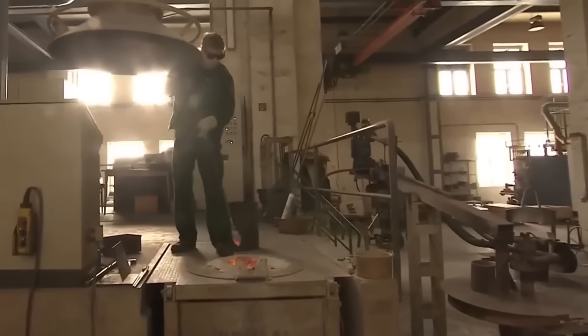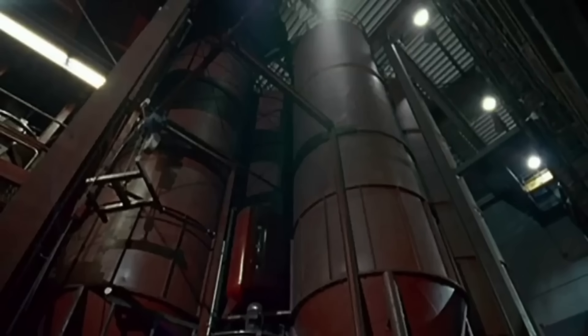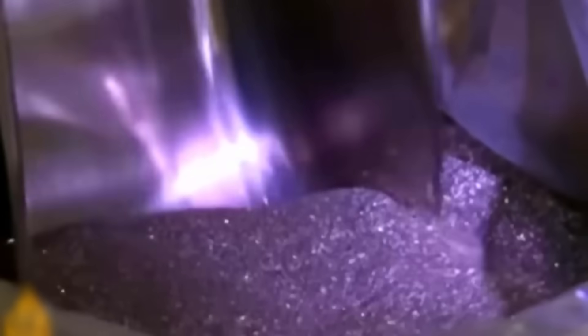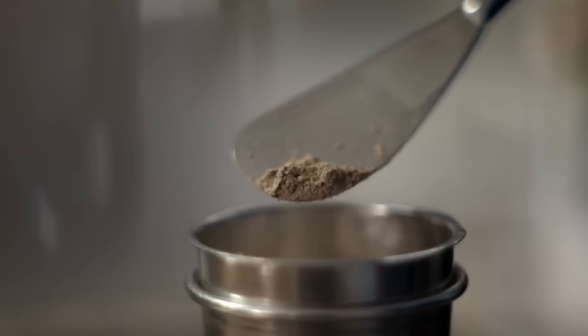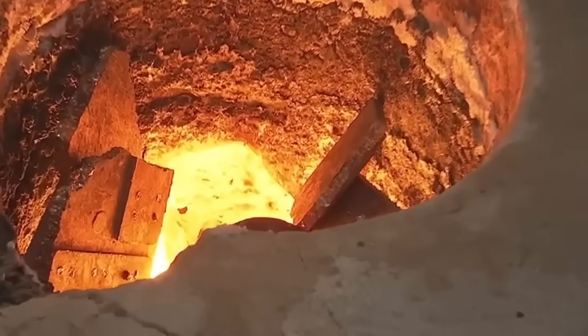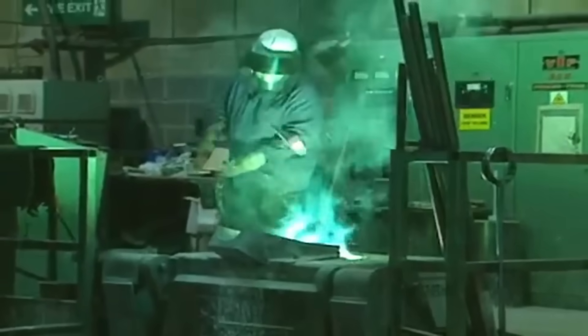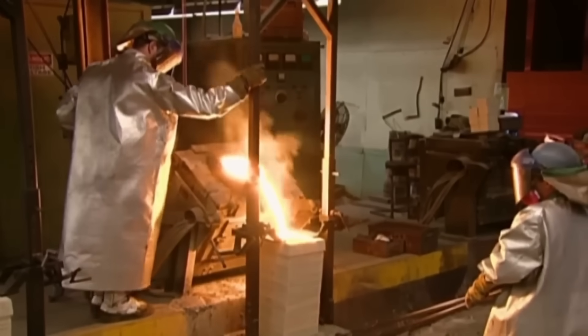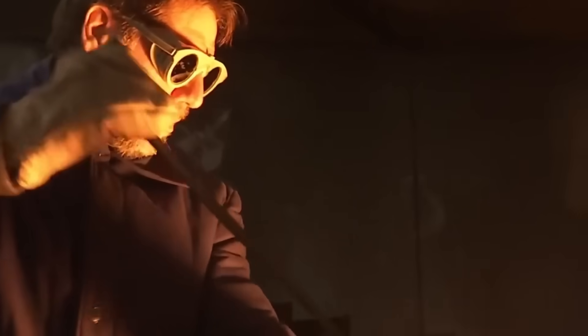The next essential step is producing the alloy powder of neodymium, iron, and boron — the base of neodymium magnets. All materials are stored under inert gas to prevent oxidation, especially neodymium, which reacts easily with air. The three elements — approximately 30% neodymium, 2% boron, and the rest iron — are placed into an electric induction furnace. The furnace creates a pulsing electromagnetic field that heats above 1,600°C, melting the metals evenly. To prevent neodymium from reacting with oxygen, the process is done in a vacuum. Once melted and homogeneous, the alloy is poured into sand molds, filling each cavity completely and reproducing every detail.